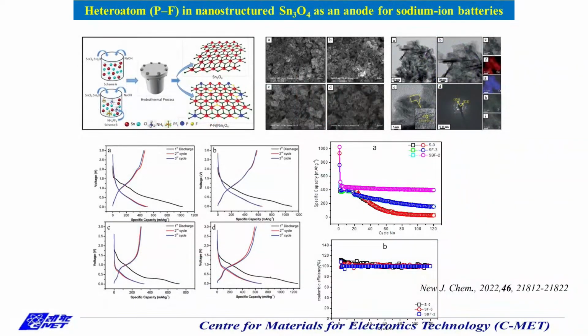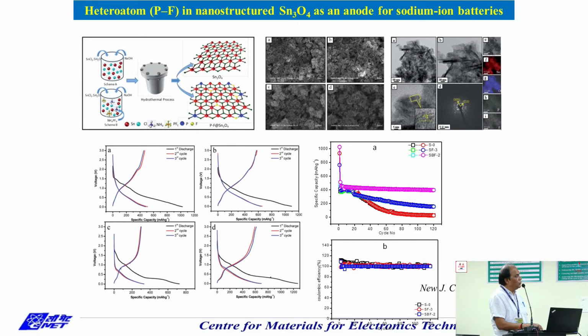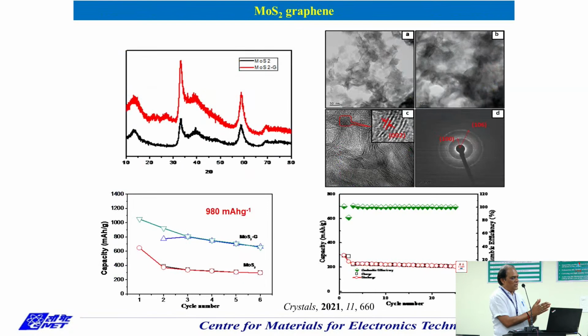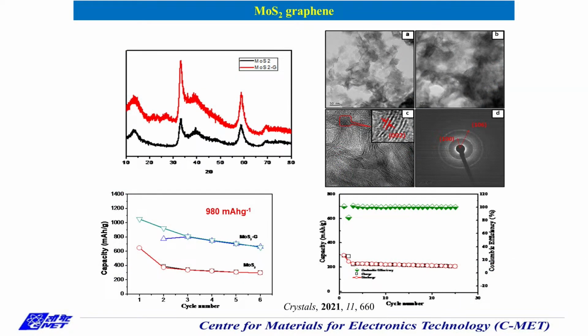Then Sn3O4 is also one of the good products which we have developed, and which can give good sodium ion capacity. All these compounds are new compounds. With these doped compounds, we will not find them in the literature. So we developed this for battery applications. Then MoS2 and graphene: whether we can use both compounds, MoS2 and graphene, together and see whether we can enhance the capacity.